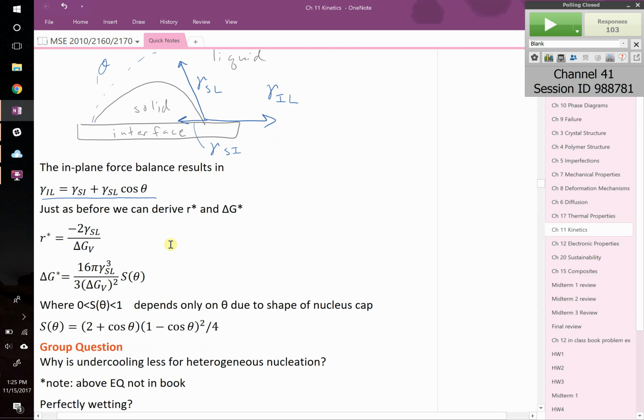Again, doing the math, you'll find that you get the exact same critical nuclei size. This is important. The critical nuclei size does not change, but the activation energy does. The activation energy looks just like it did before, except it now has this additional term tacked onto it, S of theta. And S of theta, you can calculate if you know the wetting angle. And it's always going to be a number between 0 and 1.